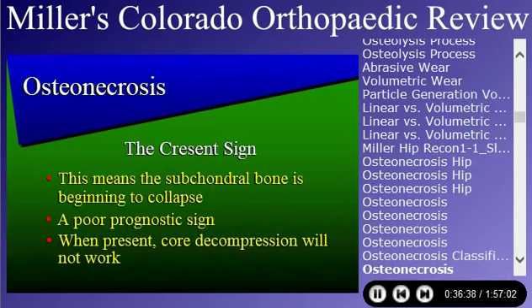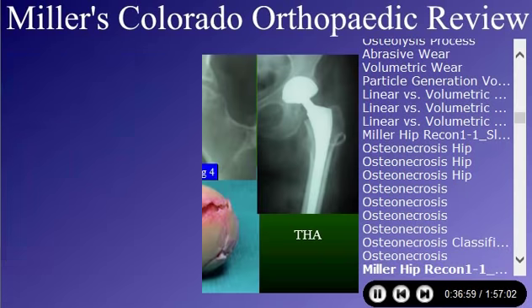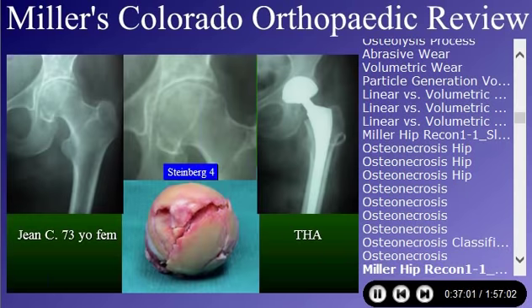And that means that the bone is beginning to collapse. It's a poor prognostic sign. So it doesn't matter on the test whether it's a Ficat 2 or a Steinberg 3. If you see a crescent sign, that's the bad thing that you want to know for the test. When present, core decompression is not going to work because once it's collapsed, you can't make a collapsed bone regenerate to a round surface. For example, if you look at this x-ray, this is avascular necrosis, and it's very subtle here. You've got a crescent sign with subchondral collapse, and then it goes on to a total hip.